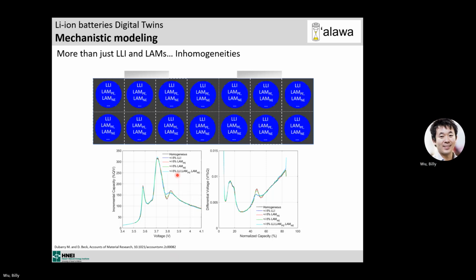Okay, so until now we focused on really homogeneous small single cells, where we all know that the larger we go, the more at risk of inhomogeneities we have in the cell. The good thing is that the model is so light in calculation that we can easily put as many as we want in parallel. So we can simulate a segment itself. We can have a lot of little segments in parallel with all different parameters and see what impact it has on the full cell. In a way, in that case, that's a pack model if you separate all the electrodes like that. But that could work to some degree for a single cell.